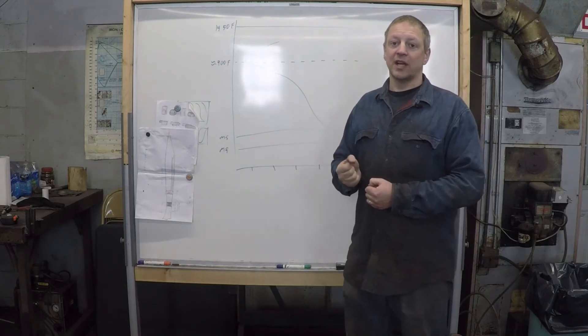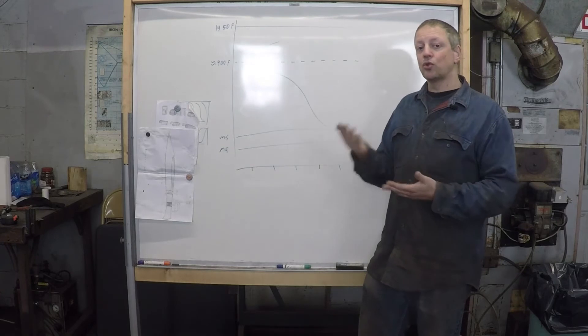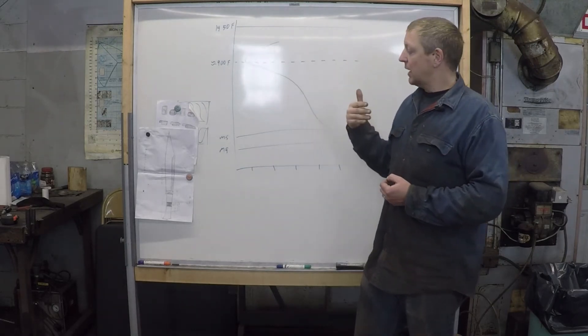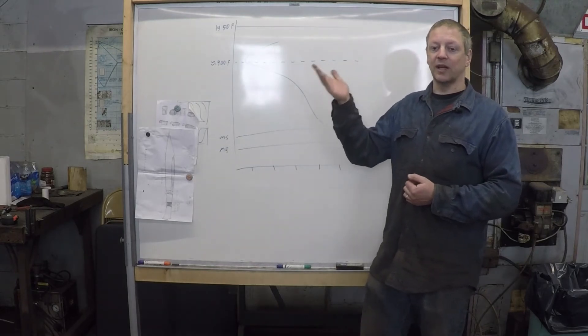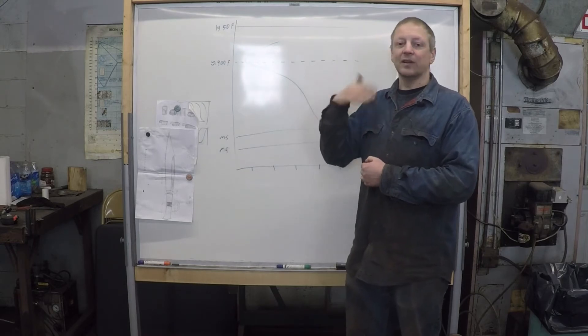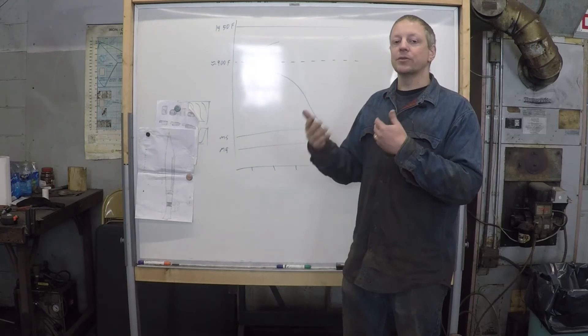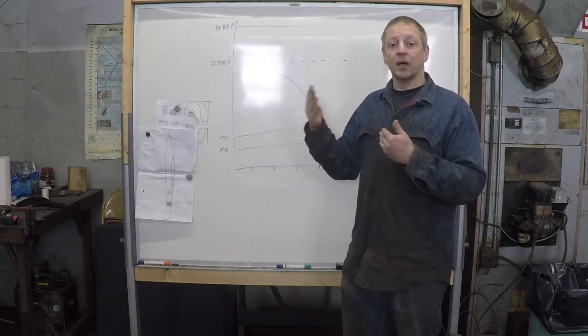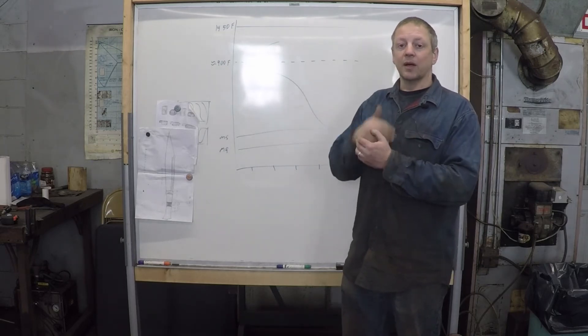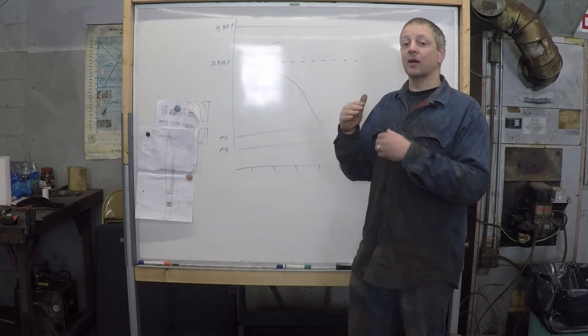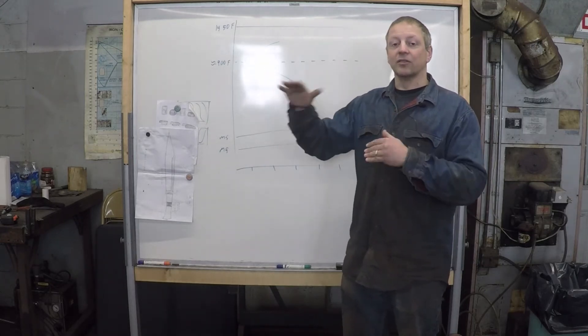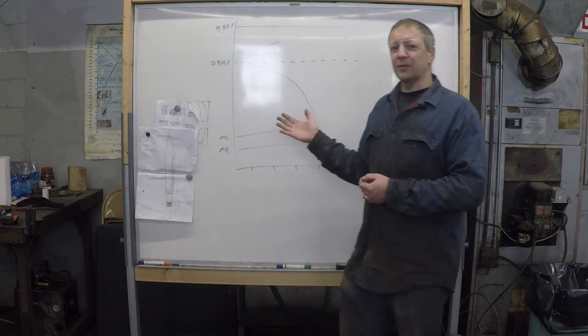Another interesting thing to note about that level of expansion, let's say you're making a katana. How much carbon you put into solution is going to affect how much curvature you get. It's one reason or one theory that I've read of why medium carbon steels such as 1050, it's very hard or it's certainly more difficult to get a nice curvature in the blade. It's a lot easier to get a nice curvature in something like W2.